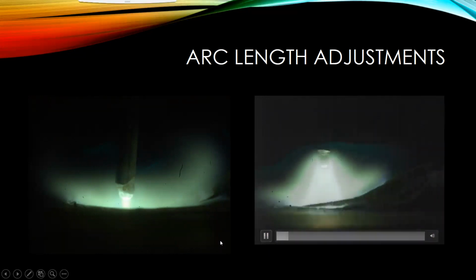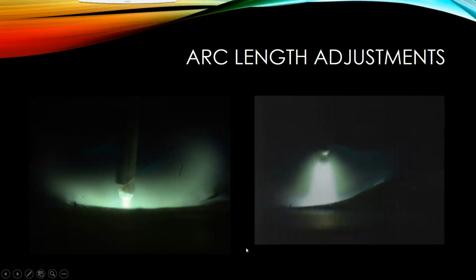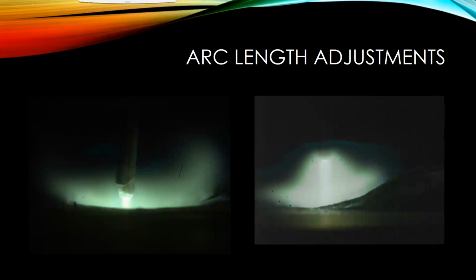So if you're swapping between joint types, if you're doing like a butt joint, you might see yourself increasing your arc length a little bit. If you're doing a corner joint or a T-joint, you might see that you're tightening that a little bit to control that arc, to control the puddle flow. But I really like this because it kind of shows you a little visual of what's happening at the end of the wire.